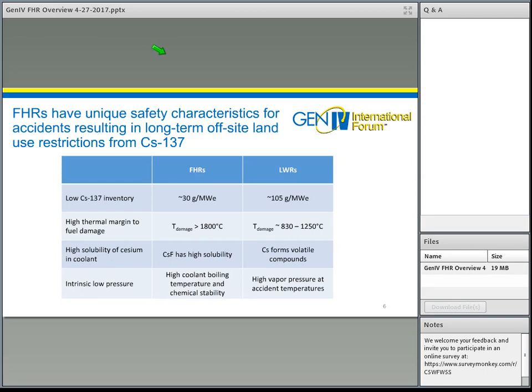One is the relatively low inventories of cesium that are resident in the core. This is because in FHRs, the fuel operates at significantly higher power density than in HTGRs, and therefore reaches full depletion more rapidly. And so residence time of fuel in the core is shorter, meaning that inventories of fission products are smaller as well. The other element is the very high thermal margin to fuel damage, which in recent AGR testing that has been reestablishing capability to fabricate these fuels in the United States has shown capabilities to retain fission products to temperatures actually in excess of 1800 degrees centigrade.